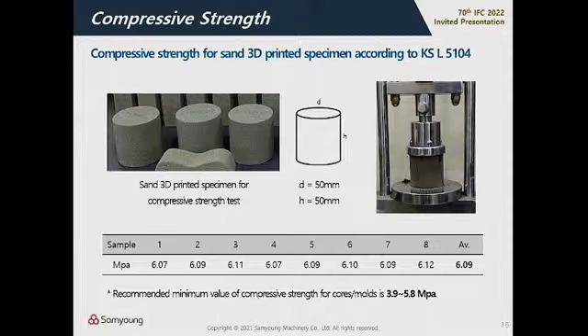The second test is about compressive strength. We tested compressive strength for the 3D printed specimen according to the standard. This picture shows the actual 3D printed specimen, and also the test equipment. This table shows the test results for 8 different specimens, and the average compressive strength is 6.09 megapascal. The recommended minimum strength for cores and molds is 3.9 to 5.8 megapascal for various applications. So the result was much higher than that.